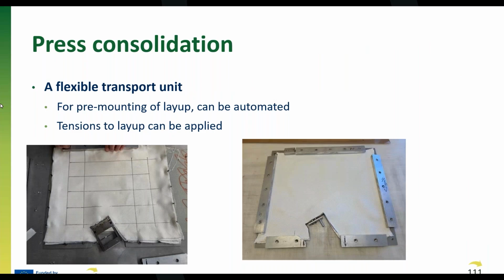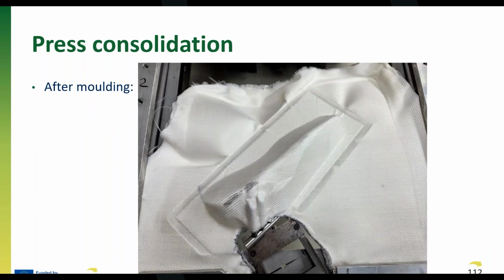But to be able to do these things, it's not only the tooling or the system, you also have to transport the materials. And we built a transport unit where you can pre-mount your laminate, and this means that you can be offline and you will automate this. And then you can also control the tension and other things on the layup, and it's easy to transport. So next one. And there you see the formed materials after the molding, and this one is a standard size. We have not minimized the materials because you can actually design it so that you don't use so much material as here, but this is a flexible unit that you can use for many different applications. Next one.